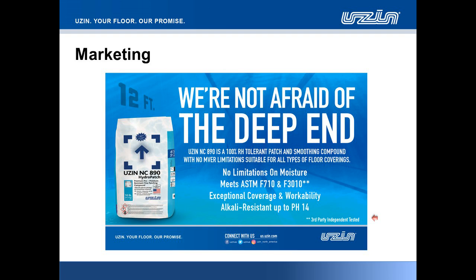And about the bond strength, F3010, which is for installing moisture mitigation using two-component epoxy systems, also calls for at least 200 psi of pull-off strength of the substrate. And we can say that this patch easily exceeds 200 psi of pull-off strength, or direct tensile bond strength, and also keeps the strength high. It does not deteriorate over time.